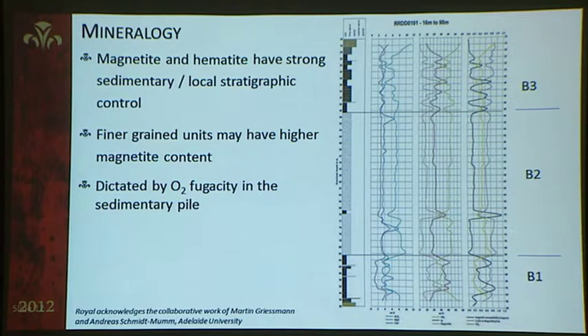And the next stage of that we're looking to do is actually working out the timing of this mineralogy. And here you can see one of our lith logs of our holes at Razorback and the correlation between the downhole magnetics and the lithologies, displaying the stratabound nature of the magnetite, where, as per those images before, you have Unit B1 as probably the highest concentration, followed by Unit B2, the tillitic ironstone, and B3, the interlaminated ironstone.